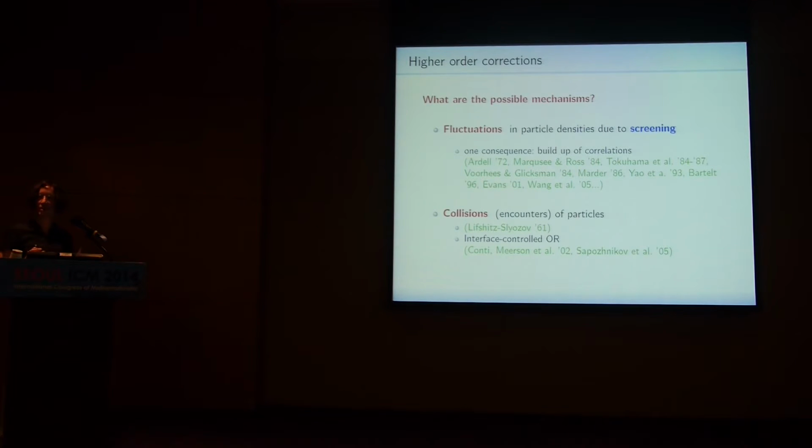You look at it, you find a large particle. It is large because it's more likely to be surrounded by smaller than average particles. And because of that, it can also grow faster than predicted by the mean field theory. And similarly, of course, a small particle is more likely to be surrounded by larger ones, and then it shrinks faster than predicted by the mean field theory.